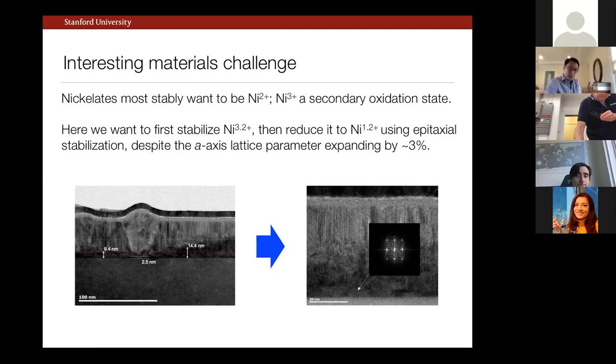Now, what the Kyoto people first showed us, and we're also seeing here, is that doing this in thin films has a particular advantage, namely that we're using strontium titanate here, but typical perovskite substrates are stable against this reduction reaction that we're using to transform the nickelate. And therefore, not only does it provide a template, it allows you to do something you can't so far do in bulk powder samples, namely orient a single crystal thin film, or at least in this case, just in the vicinity of the interface, stabilize this structure. So that's actually quite important and powerful for our work.